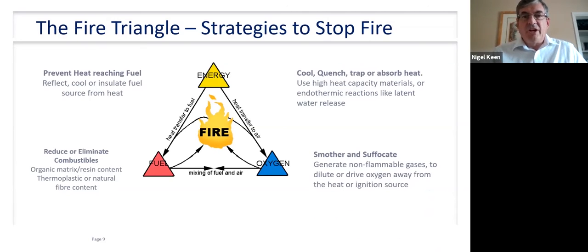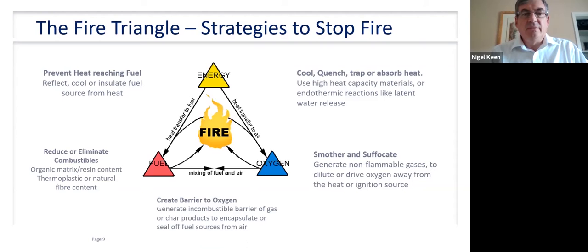You can actually generate gases and smother the oxygen. If you can drive the oxygen away from the fire by creating other gases, like nitrogen or carbon dioxide, something non-flammable, then you can drive the oxygen away from the fuel source and stop that happening. And finally, you can create other barriers. You can create an incombustible barrier. You might be able to get something to intumesce, create a nice glassy shield and seal off the unburnt laminate from the air.